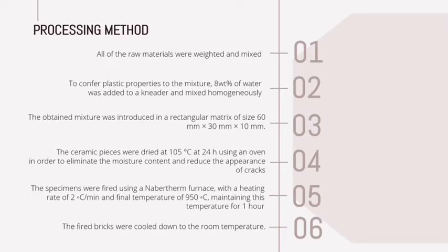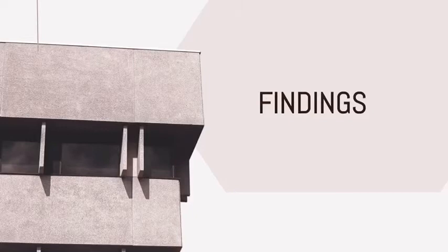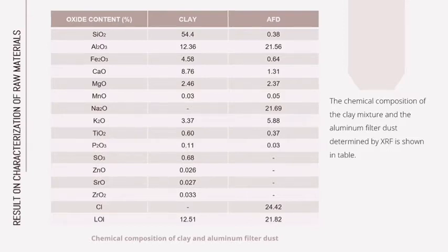The specimens were fired using a Nabertherm furnace with a heating rate of 2 degrees Celsius per minute and a final temperature of 950 degrees Celsius, maintaining this temperature for 1 hour. The fired bricks were cooled down to room temperature. Finally, this is the method. Ten samples per series were produced using all the raw materials, which are the clay and the AFD, aluminium filter dust. Next we will be talking about the findings, the results on the characterization of raw material.